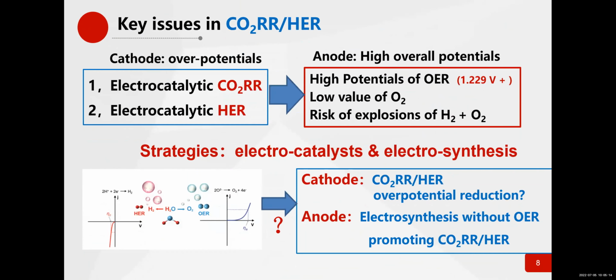The main issues now in these 2 kinds of reactions, carbon dioxide reduction and hydrogen evolution, are, first, at the cathode itself: how to reduce the overpotential of electrocatalytic carbon dioxide reduction and the overpotential of the hydrogen evolution reaction. The second one is even more important, at the anode. In company with the carbon dioxide reduction and HER is the OER, the oxygen evolution reaction. Such reactions need very high potentials. Theoretically, it is about 1.23 volts, and we also need some overpotential. That means a lot of energy will be consumed in the OER at the anode, and then we get oxygen, which is of low value, and there is also a risk of explosion of the mixed hydrogen and oxygen.